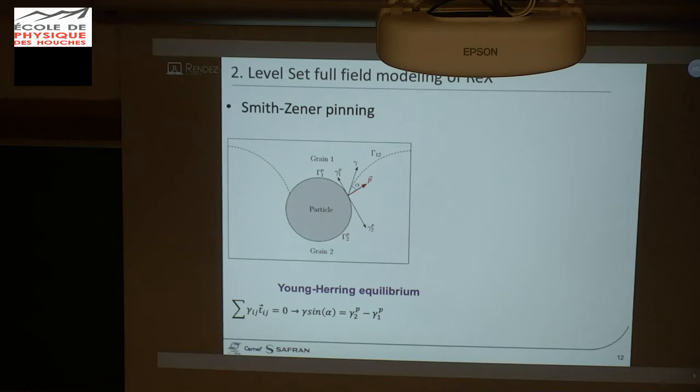What you can see in my scheme is that in dotted line you have one grain interface, and in the gray part you have a static second phase particle. The Smith-Zener pinning aspect is quite simple to understand because it is exactly the same equation that you have at a triple junction between three grains. It's finally to respect the Young-Herring equilibrium at the interaction position of the grain interface, but here not between three grains, but between two grains and a static particle.